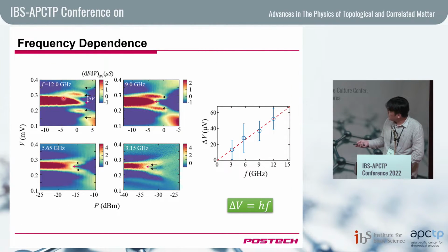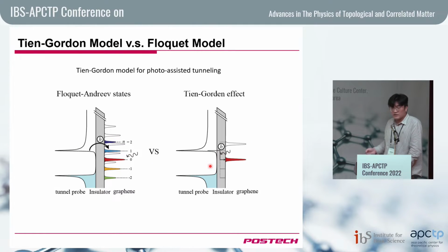For the last test, we changed the frequency, of course. If you change the frequency of the light, you would change the gap between the Floquet state and the original state. So if we decrease the frequency from 12 to 3 gigahertz, you can see the distance between these peaks decreases, to the level that we start to lose the resolution, so our energy resolution was on the order of 20 micro eV. But within that range, the delta V, which is the gap energy between the Floquet state and the original state, was proportional to the frequency with the proportionality constant being Planck's constant.